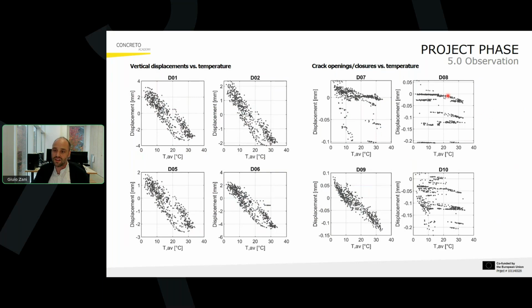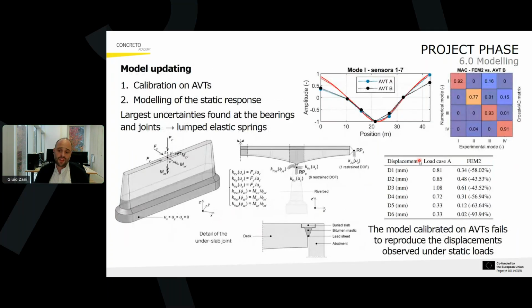While in some cases, and this is the case of cracks or transducers monitoring crack openings, we see that we don't have a clear linear correlation. So this means that this is a phenomenon which is not strictly related to temperature variations.